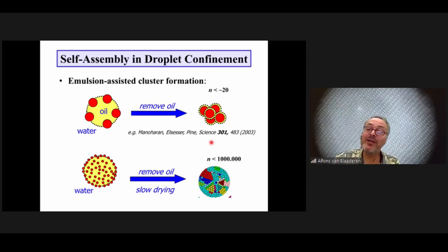But what is relatively new is that we are focusing on the self-assembly of the particles that are not at the interface, but that are dominated by the self-assembly of the particles inside the droplets. So in this work of Pine, you create beautiful clusters, which are hugely influenced by the strong drying forces on the surface. Here, we look at the self-assembly of the particles in the bulk.